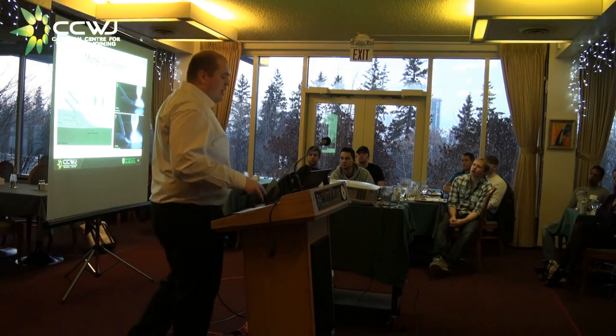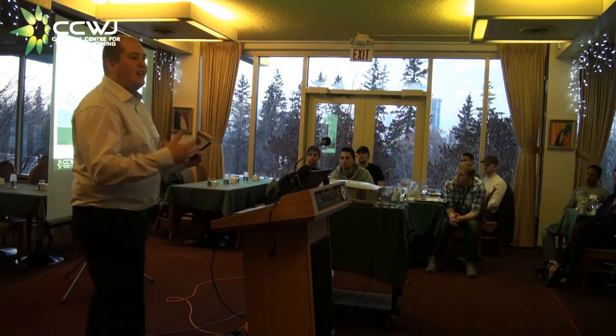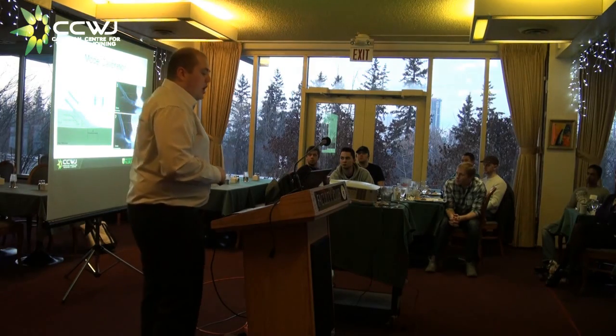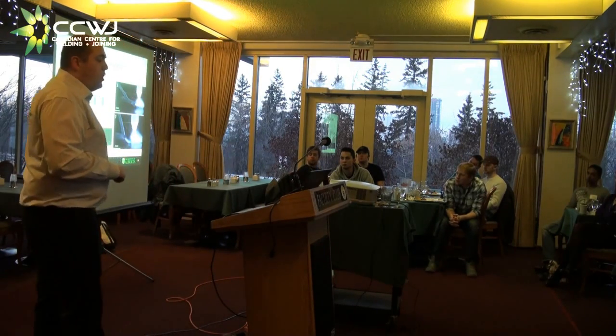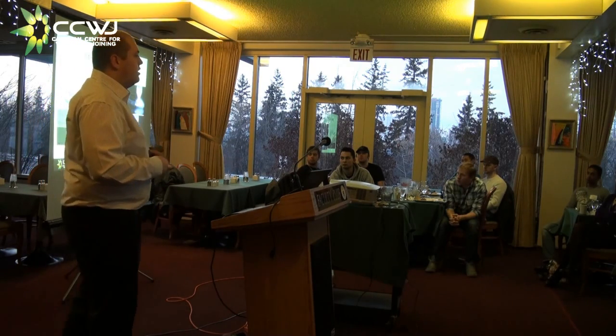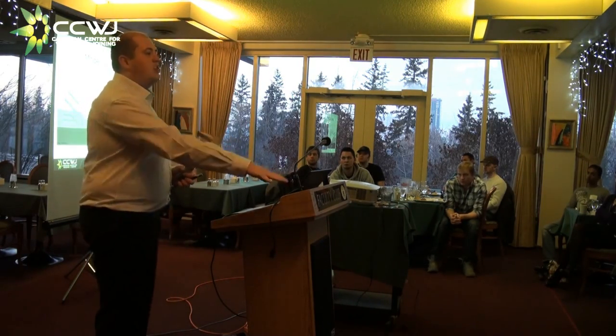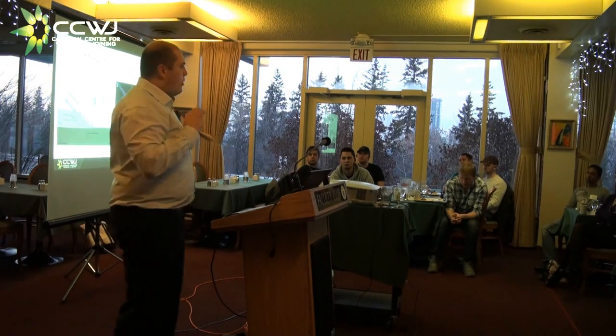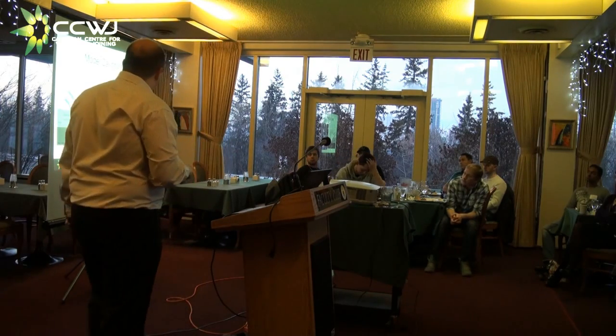Now, what's good with a model that hasn't been calibrated somewhat? So this was kind of a little bit of a brain cramp again that I did last summer. How can we start moving from the theory and going into the practical and linking them together? How can we make it work? We did a couple different things. One of the things was use our high-speed video camera to characterize where the melting was happening along the length of the wire. If we didn't have enough current, we could basically see the wire plunge right into a weld pool. If it had too much current, it would actually prematurely melt and neck off and then break contact with the weld pool. When we had things just right, we could characterize the distance between the wires and the electrodes.